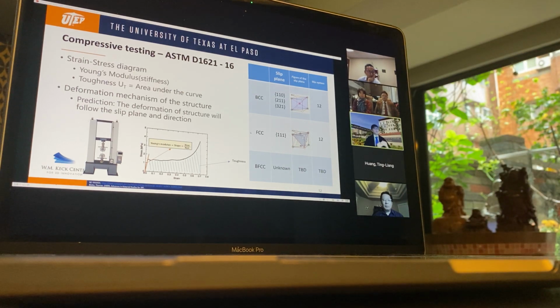For compression testing, we use an instrument compression fixture following the ASTM standard number D1621 to tell us the mechanical properties of this product. So we can get the stress diagram in a compression test. From this curve, we can calculate the Young's modulus, which is the slope of the first curve, and the toughness, which is the area under the curve.